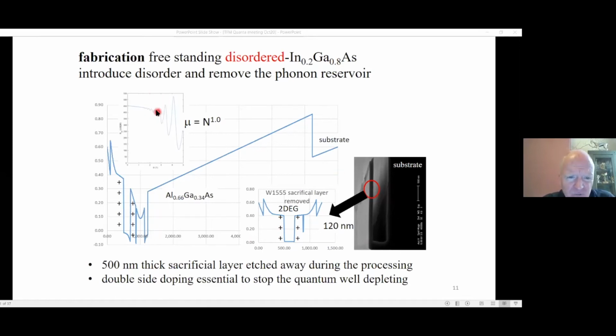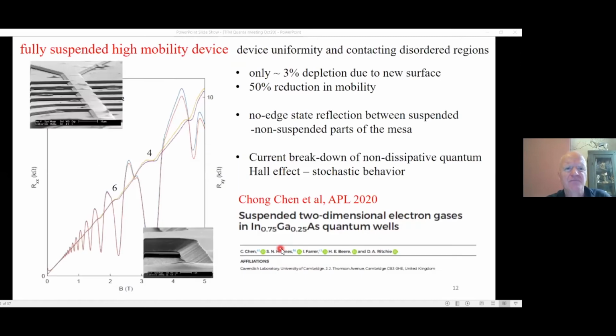Interestingly, if we look at their magneto-transport properties, so this is putting a perpendicular magnetic field on, in the higher temperature regime we can see a Shubnikov-de Haas effect, change of carrier density. The mobility that we measure depends on the carrier density to the power 1. That tells you straight away that the electrons in the quantum well really feel that disorder. It's not remote ionized impurity scattering, it's ionized impurity scattering from the doping that we put in at the interface.